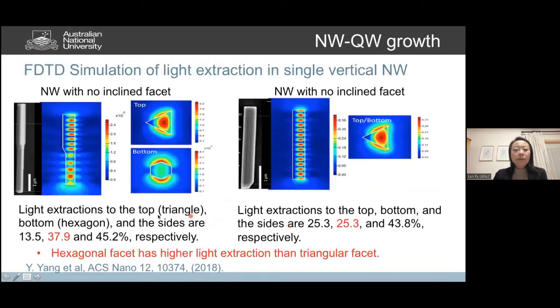Of course, also from the simulation, we can see that for this inclined facet nanowire, I think there's a typo here, from the bottom of the nanowire you can see that the light extraction is much higher than the triangular surface with hexagonal bottom. That means hexagonal facets may have higher light extraction than that. And that's what we want to see: can we grow hexagonal facet nanowires?